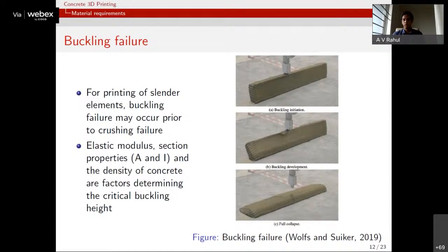Now, if you look at the buckling equations that we derived for hardened concrete, the same would apply here. There, the material parameter that influences the resistance to buckling is the elastic modulus. So the material should have a sufficiently high elastic modulus once it's deposited to prevent buckling type of failure, especially if you're looking at very thin elements.